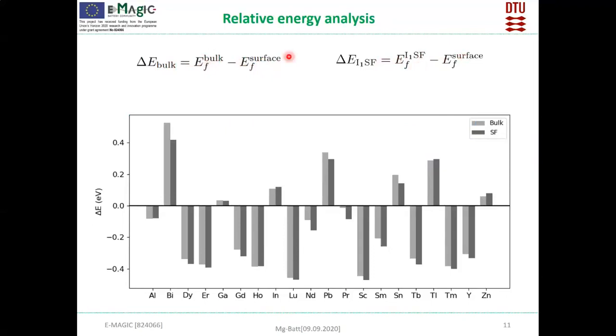any of these should be negative so that our dopant will stay inside the bulk. And when we studied the stability, these are the 20 dopants which are known to be stable after our second criteria. And we observed that aluminum and most of the rare earths show promising results. So they show to stay in the bulk. So these elements are favorable to stay in the bulk. That means we get a dopant-free surface when we alloy with these dopants.